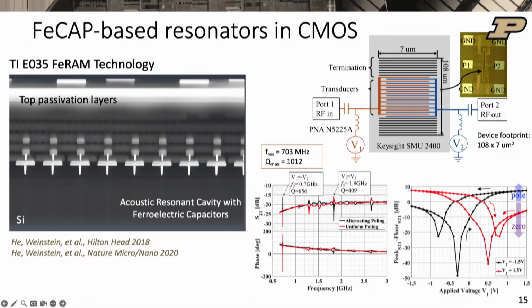And so depending on the bias voltage that's across each one of these, you can pull the film up or down, which changes the phase with which, if I apply voltage, do I strain or do I expand that little segment of my structure? So you can imagine I can excite different modes by changing the polarization on these devices. So we were able to demonstrate pole zero switching.